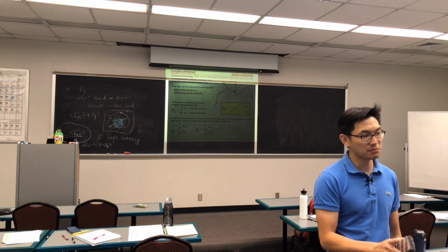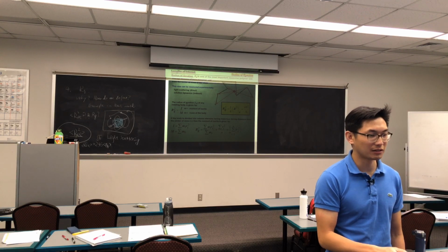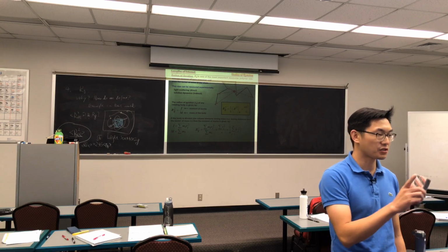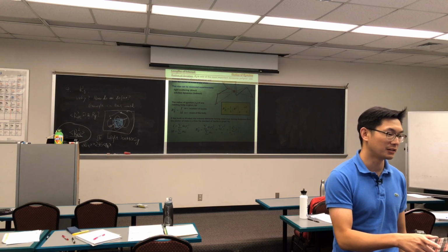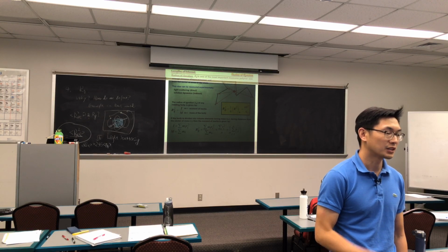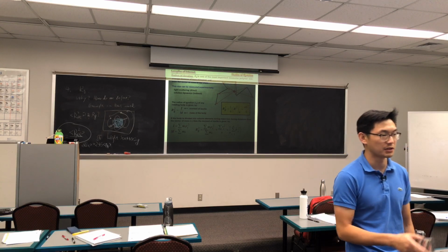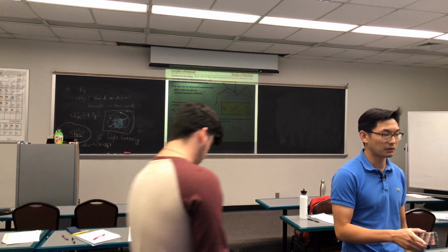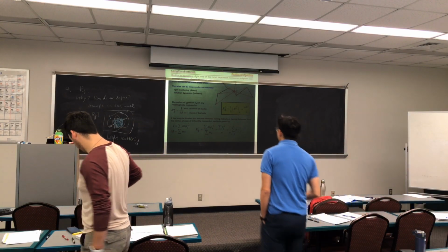You will, if you combine it with molecular weight. You can get a relative understanding of how rigid your polymer is. For a given molecular weight, let's say I have a soft polymer versus a very rigid polymer, both with about 10,000 repeating units. If it's more rigid, your Rg will go up. So in that regard, if that's the question you ask, yes, you will get relative information out of it. But you absolutely have to measure molecular weight correctly and do a fair comparison between both.